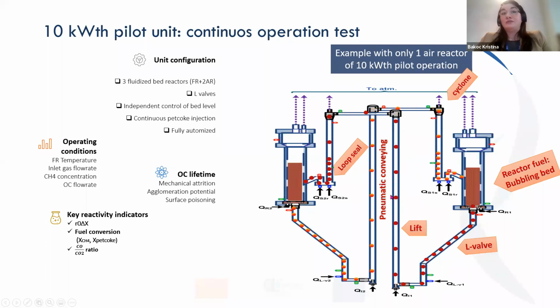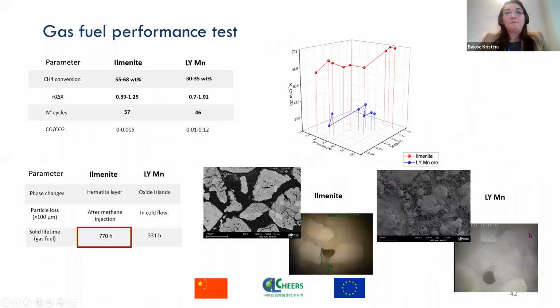What is important for this unit is that it allows us a closer representation of the lifetime of the oxygen carrier in the actual unit, and it can show us the agglomeration potential of different oxygen carriers. Of course, throughout the entire test in the pilot unit, we would closely follow the key reactivity indicators, which are once again the values of R0 delta X, or oxygen transfer capacity, different fuel conversions that are targeted to be as high as possible, and also the ratio of CO to CO2 at the outlet of the fuel reactor, which we aim to be as low as possible to indicate good gasification of the Petcoke.